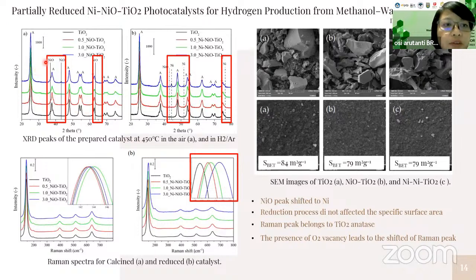Here, the first graph is the XRD peak. They try to create the composite of NiO and TiO2 by the sol-gel method. For the first one, they only annealed the particle at 450 degrees Celsius in air, and we can see from the XRD peak only titanium dioxide anatase, and we can't find the NiO peak. However, when they calcined the catalyst at 450 degrees Celsius under H2 and argon gas, you can see that they also produce titanium dioxide, but the peak of NiO shifts to Ni. Here we found a small amount of NiO, but almost all NiO from figure A shifts to the Ni peak.